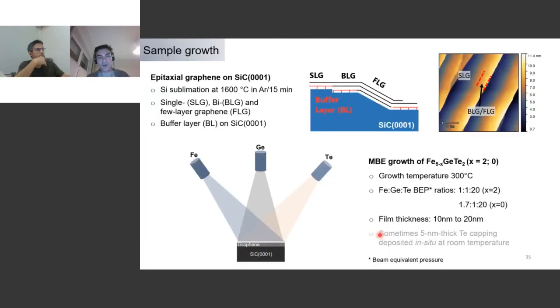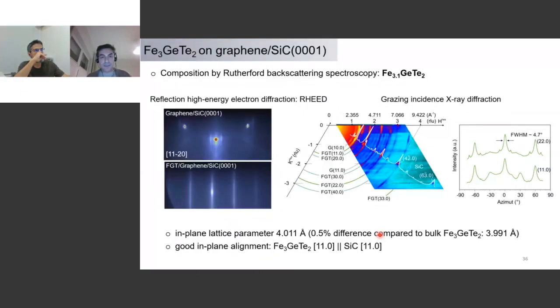And so again, here our goal was to go for large-scale epitaxy, understanding large-scale epitaxy of this type of materials. We go to another MBE system where we have sources for that, and we try to grow this iron germanium telluride on top of graphene, again using epitaxial graphene as a nice substrate for van der Waals epitaxy studies. So I go very quickly here, but the bottom line is that we have done in situ reflection high energy electron diffraction, as well as grazing incidence XRD diffraction, that shows us that we've been able to grow this iron germanium telluride on graphene, epitaxially grown.